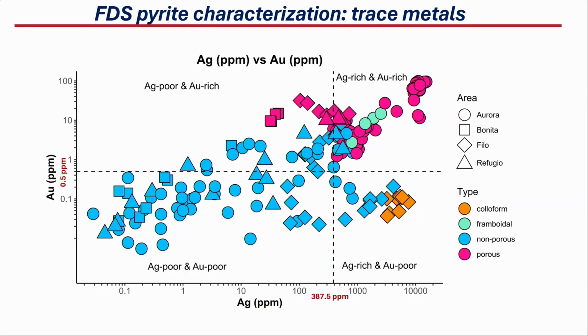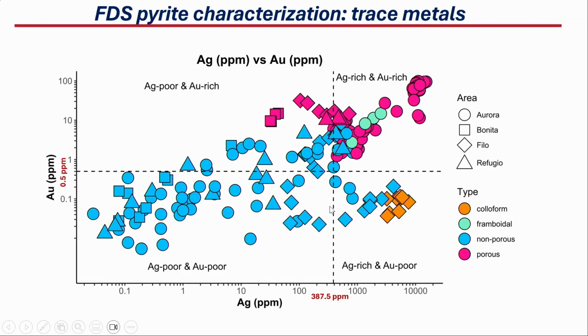So if we see the overall distribution, this is a diagram with silver on the x-axis and gold on the y-axis. I made the normal score for all the different trace elements in my pyrite. So I determined the boundaries to say, okay, this pyrite is gold rich or gold poor, just based on the normal score. So these are the different boundaries to set gold rich or gold poor areas. And here what we can see is that we have non-porous pyrites, in light blue, and most of them are silver and gold poor.